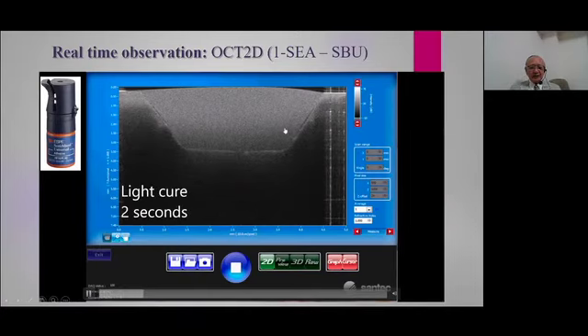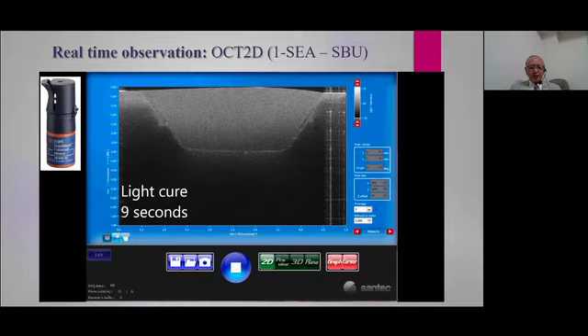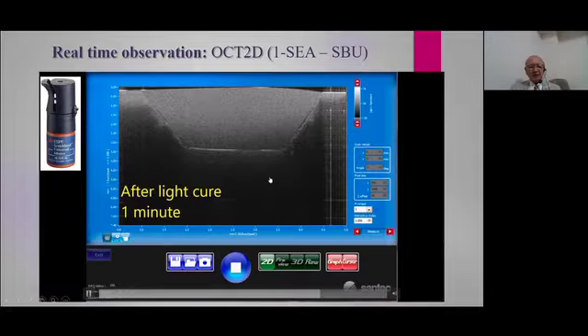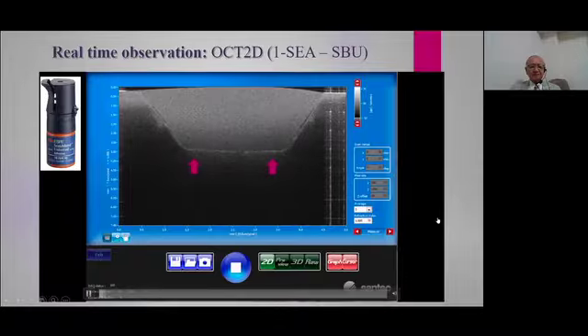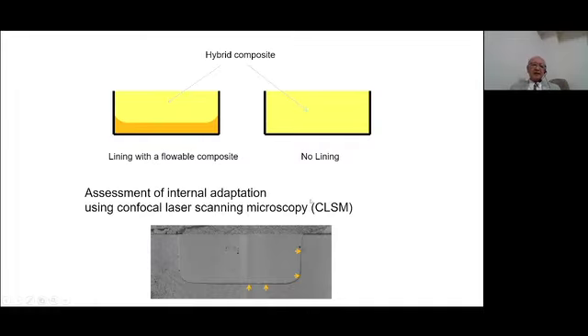Now light curing started, and look at this part. During light curing, of course, shrinkage of composite occurs already. Now you see the white line. The gap started mostly and extended to all the cavity floor dentin. Even after light cure stopped, still the shrinkage stress remained in the composite resin. That's why sometimes the gap is extended. Okay. Now, like this, the gap is very easily created in the cavity.